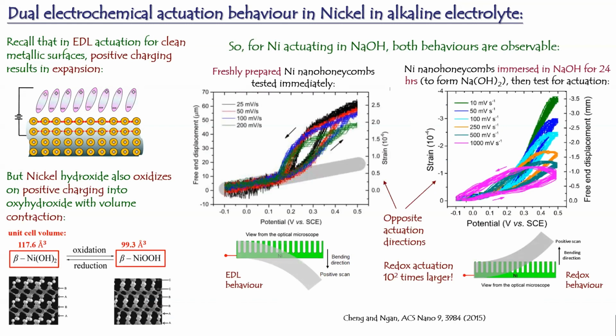Okay, so when you freshly prepare these nickel nano honeycombs, and then do the actuation test immediately, you would not form the hydroxide or oxide. Then you would have the EDL mechanism, and you see that the strain is positive, meaning that it's expansion. But if you prepare these nano honeycombs and just dip them into the sodium hydroxide for like a day before the actuation test, the material will oxidize into the hydroxide. And then as you now carry out the actuation test, the strain is now negative. Okay, so we observe these two opposite behaviors.